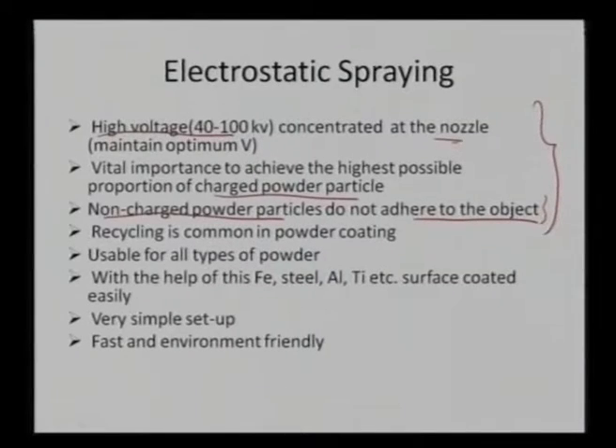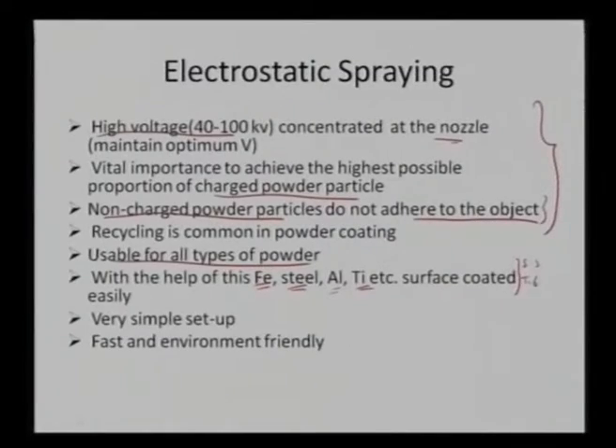It is usable for all types of powders, and more than that, we can utilize electrostatic spraying to coat iron, steel, aluminum, titanium, etc. As we know, for an implant material, we need the material to be good enough in terms of strength, and hence metallic materials come as the emerging candidates. So, either we have stainless steel, titanium-6 aluminum-4 vanadium, or cobalt chromium alloys, and we also saw other materials such as tantalum or even magnesium and many others. All those are nothing but metallic materials. So, this process can be highly utilized in coating all those metallic implants.